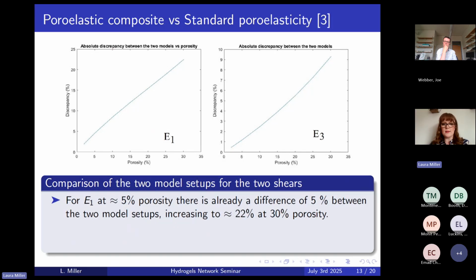So then what I did was actually plotted the absolute discrepancy between the two models. So for our E1 Young's modulus, already when we're at about 5% porosity, which is reasonably small, we see that there is a 5% difference already between the two setups. And this just increases all the way up to 22% difference at 30% porosity, which I think is quite a large and distinctive difference to have between two models when you're basically trying to describe the same thing with the two models. You have a sample of tissue that has various elastic constituents and a fluid compartment, and you want to describe it. You have two choices of models. You shouldn't see as much discrepancy as that.